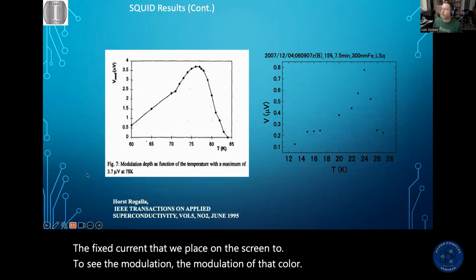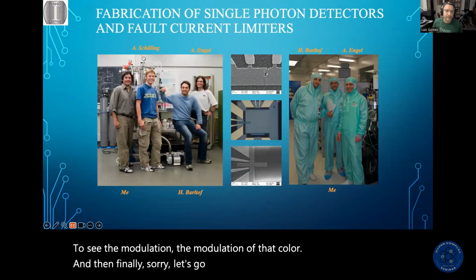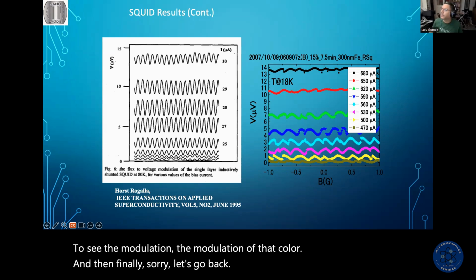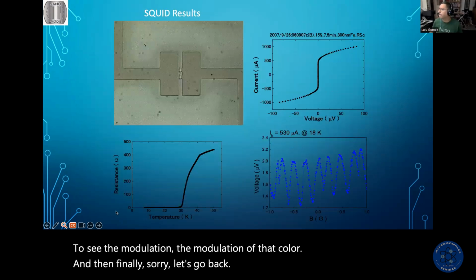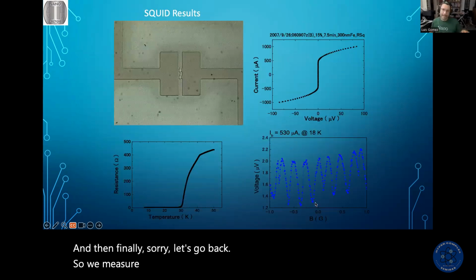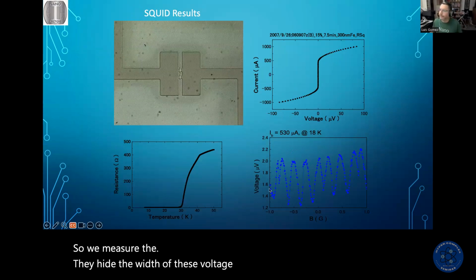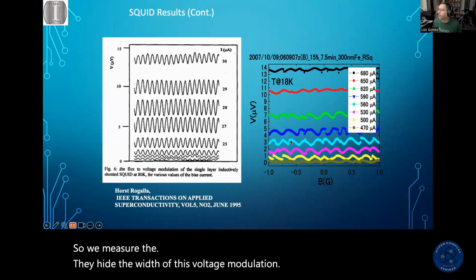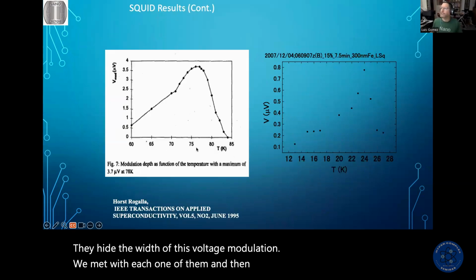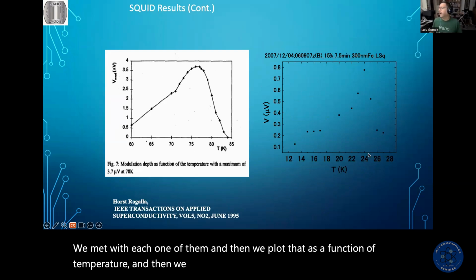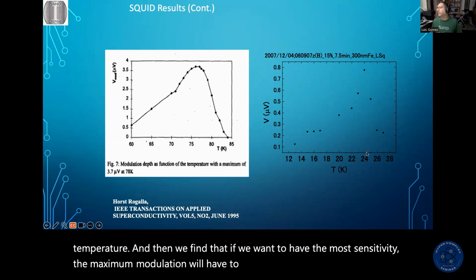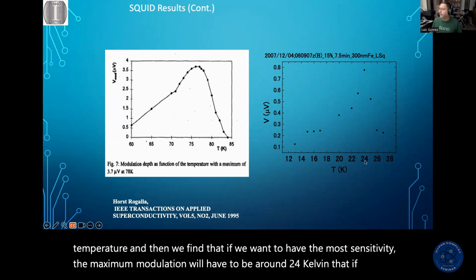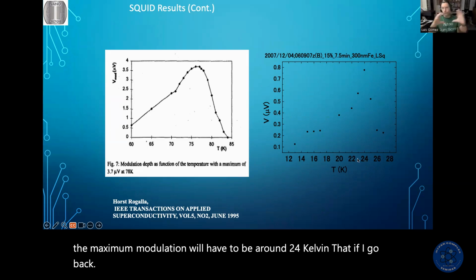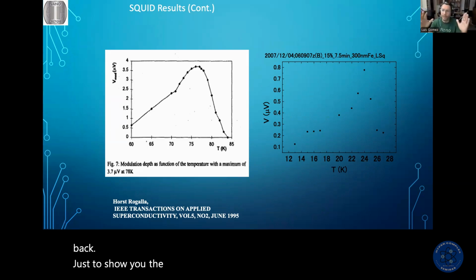And then finally, let's go back. So we measured the height, the width of this voltage modulation. We measured each one, and then we plot that as a function of temperature. And then we find that if we want the most sensitivity, the maximum modulation will have to be around 24 kelvin.